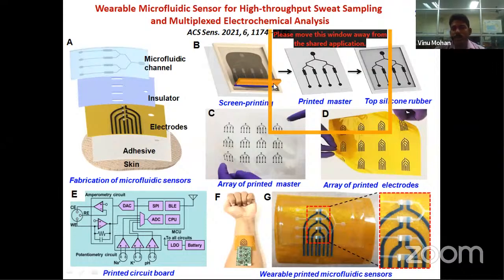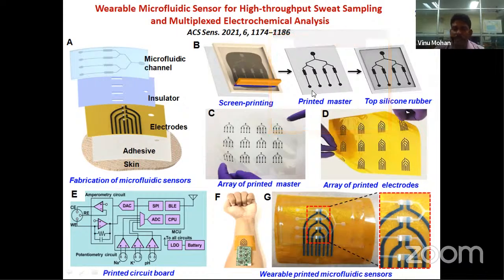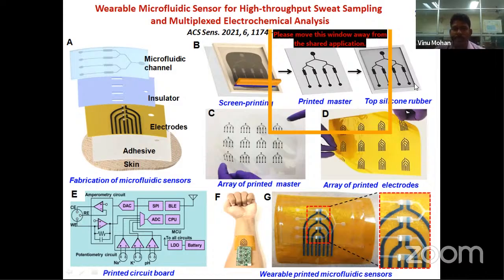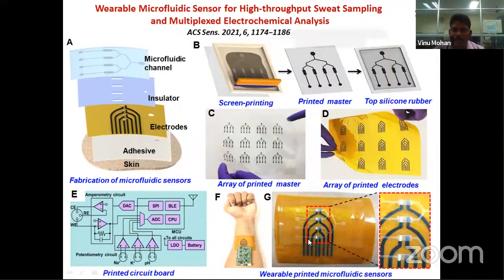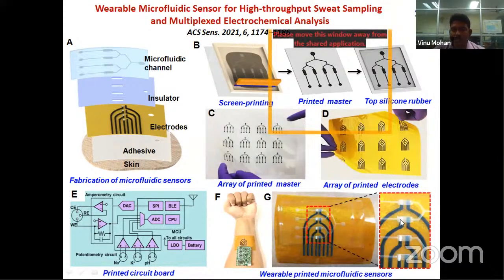But here we followed another technique, the same screen printing technique. We printed carbon ink on a flexible substrate, and on top of the pattern we printed silicone rubber, which is a flexible polymer. Silicon rubber is nothing but PDMS, the commercial PDMS, which is a very good elastomeric substrate. We can have mold transformation. So after curing this silicone rubber, we have these microfluidic channels, and we can attach these channels on top of our screen printed electrodes. As you can see, there are 4 different sensing areas, and all 4 areas are covered with these microfluidic channels.